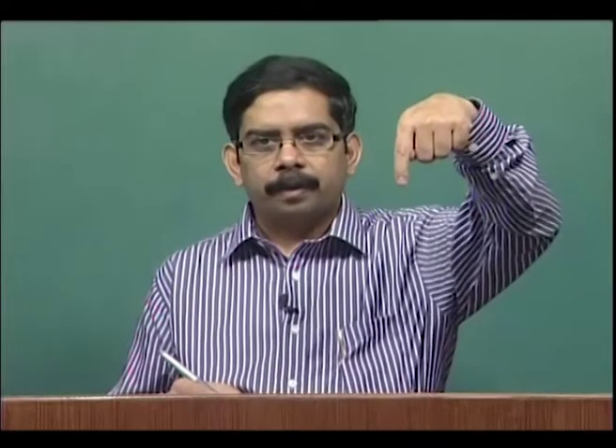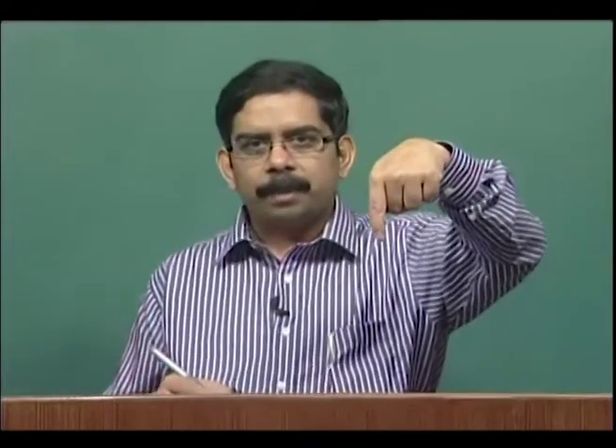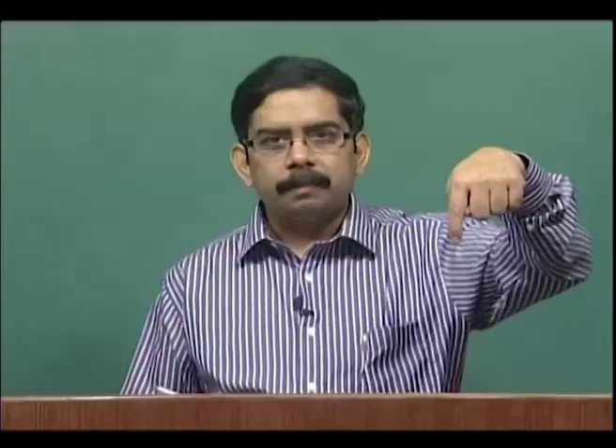But if you focus the TEM beam, the electron beam, on a particular particle, you would see this, but soon after that you would also find that the same region is getting crystallized to a ring pattern. What does this mean? The electron beam is able to crystallize that nanoparticle from amorphous to a crystalline form. So it is that fine. At the same time they are very reactive, they can even get crystallized by the interacting electron beam. Therefore we need to understand this is the sort of reactive particles that we can end up with in sonochemistry.